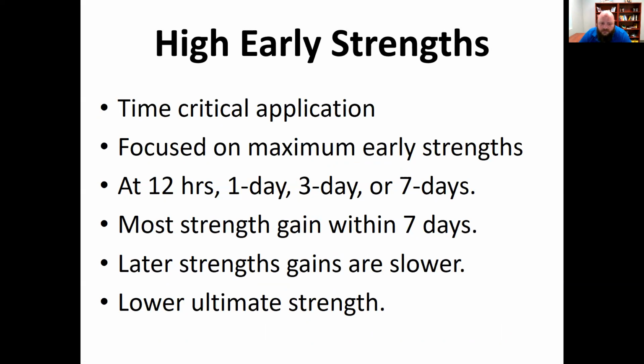We talk about high early age strength. This is really more time dependent. So you want a certain strength gain within a certain amount of time. It may be 12 hours, it may be 14 hours, 24, maybe 3 days, sometimes even 7 days. But typically we're thinking more of 3 days and below. But most of the strength gain is going to be within the first 7 days, though. And your later age strength gain, because you're trying to focus so much on that early age strength gain, a lot of times these mixes will actually plateau after 7 days anyway. So it's important to realize that.